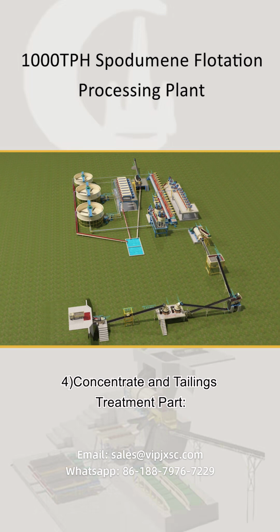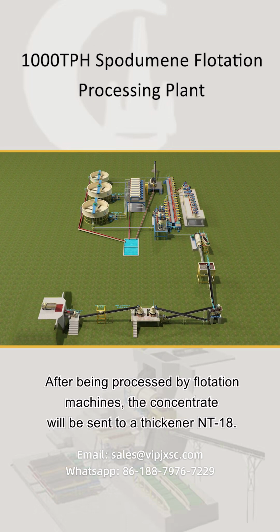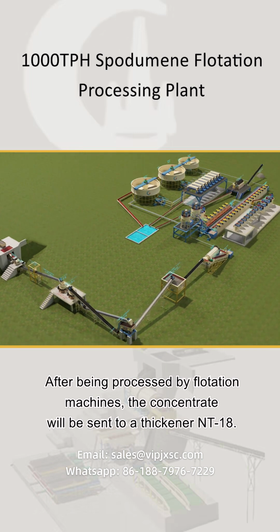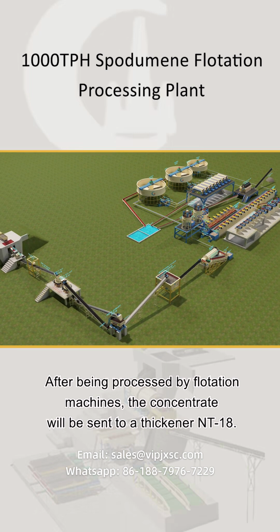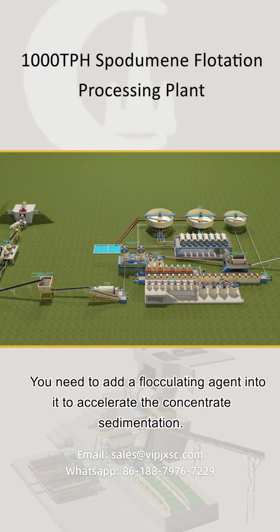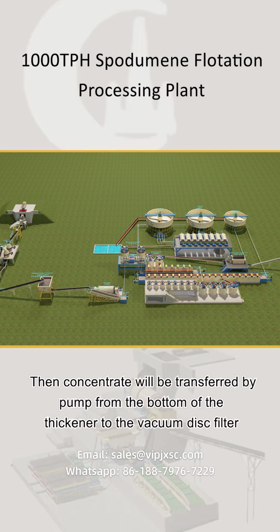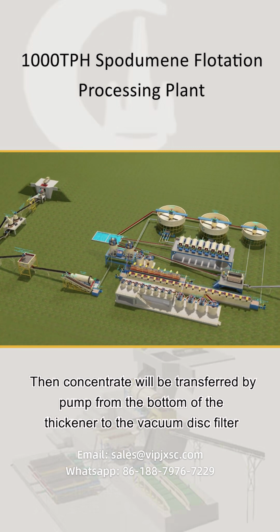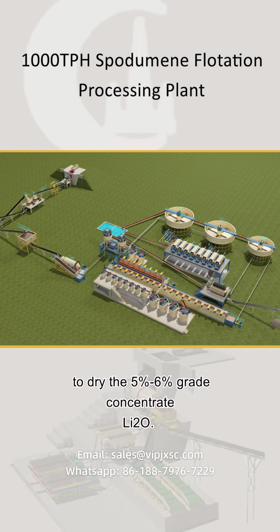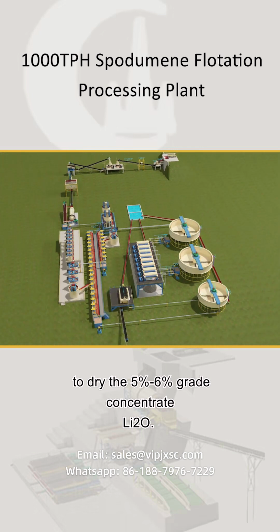4. Concentrate and tailings treatment part. After being processed by flotation machines, the concentrate will be sent to a thickener NT18. You need to add a flocculating agent into it to accelerate the concentrate sedimentation. Then concentrate will be transferred by pump from the bottom of the thickener to the vacuum disc filter to dry the 5 to 6% grade concentrate lithium oxide.